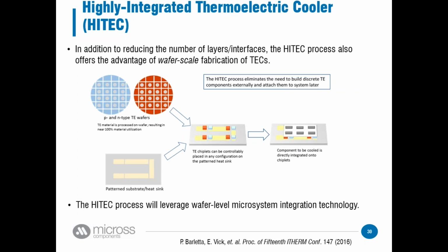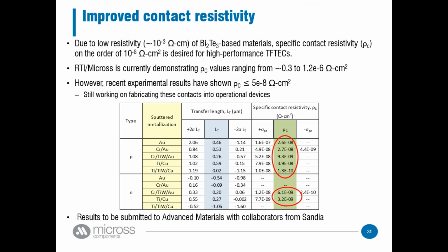Again, presented at iTherm. We also have a patent application on this. Another problem, one of the things I wanted to talk about as we wind up the technical part of the talk, one of the big challenges with working with bismuth telluride: we talked about the low conductivity, we talked about the low band gap, and what that means is that the contact resistivity of these materials has to be very, very low. In nitrides, 10 to the third is a good contact resistivity, Ed? Maybe 10 to the fourth? When you're talking about thermoelectric devices, we're talking about 10 to the minus 8 ohm centimeters being what we need. We're at about 10 to the minus 6 right now to get the 250 watts per centimeter squared. But in order for our modeling to make our devices work and improve, you need to get down into the 10 to the minus 8, even 10 to the minus 9 range.